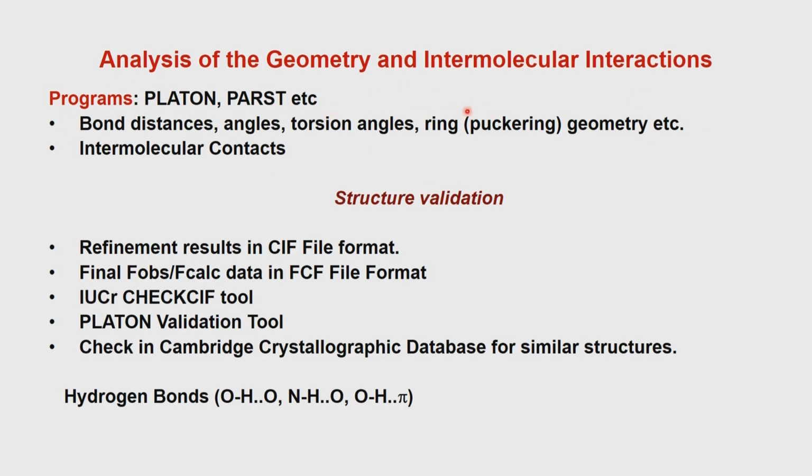After that, we have to see there are no funny contacts. Suppose now you solve this structure and the structure develops some contacts which are very much shorter between intermolecular contacts, then you know something is wrong. So, anything wrong at this stage of the geometrical calculation one can find out and redetermine the structure. So, this is a place where the reliability of the structure determination is evaluated.